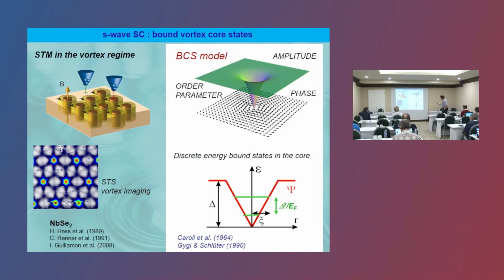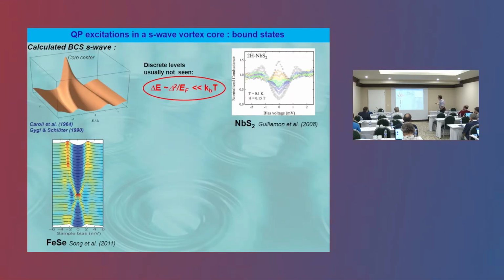So rapidly, everybody knows that you have the vortex where the order parameter goes to 0, and the main consequence concerning the excitations that you can put inside the core is that in the case of an S-wave superconductor, these excitations should be localized. So there are finite energy states. The spacing was predicted to be of the order of delta squared over EF, delta being the superconducting gap. And so at the center of the vortex core, a lot of these states should be visible, but the spacing between these states is so small, delta squared over EF, that they should not be seen individually, even at the lowest temperature.